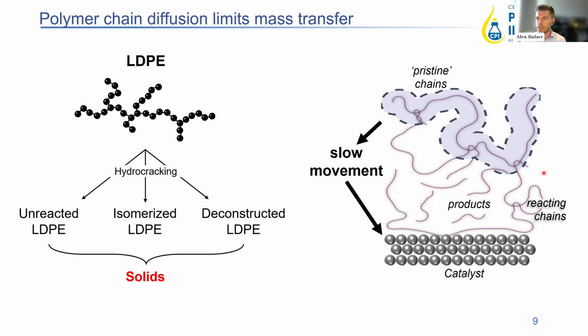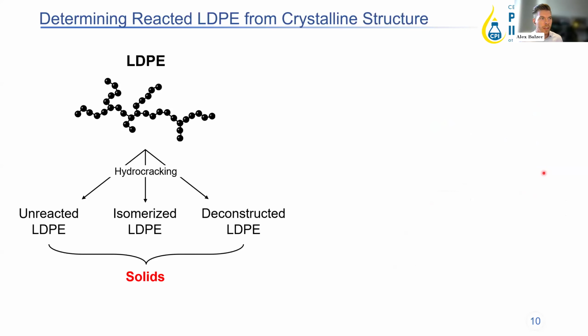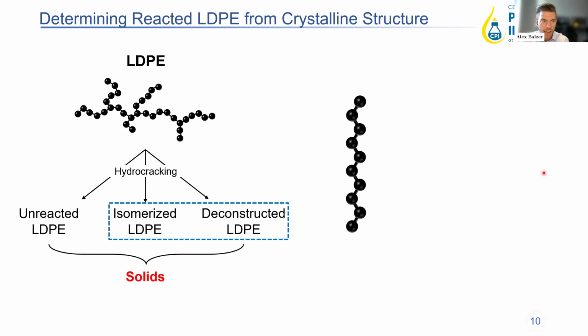And then as the reaction time increases, slowly the viscosity of your overall reactor decreases. And so you're going to get more and more chains with higher and higher diffusion during this. And that gets that broadening of the molecular weight distribution. But we also wanted to look at the other parts of these solids, which is the isomerized and deconstructed LDPE, which can be characterized as the reacted LDPE, because regardless of what transformation it went through, these two products had to interact with the catalyst.